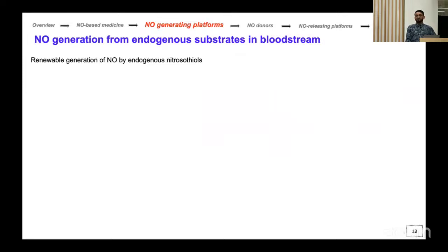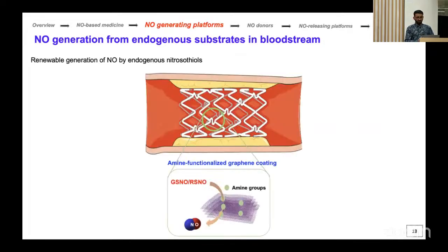So we are using basically the NO sources from the bloodstream. This is an approach where we use amine groups on top of the graphene, and then we coat graphene onto the stent, a layer-by-layer coating. The first layer will interact with the bloodstream, and then the second layer, then the third layer. So that's how we can make it a renewable generation of nitric oxide over a long term.